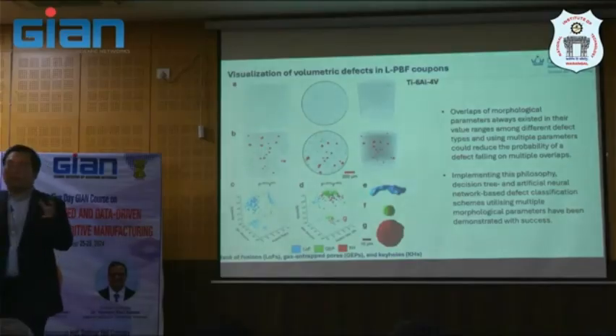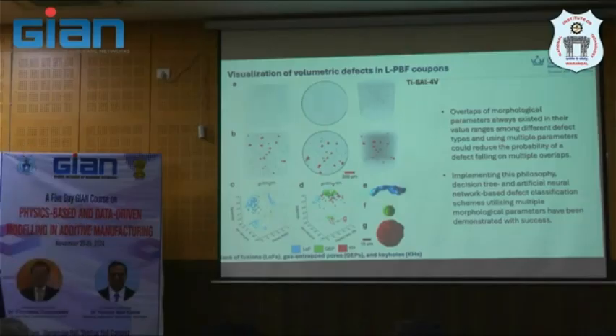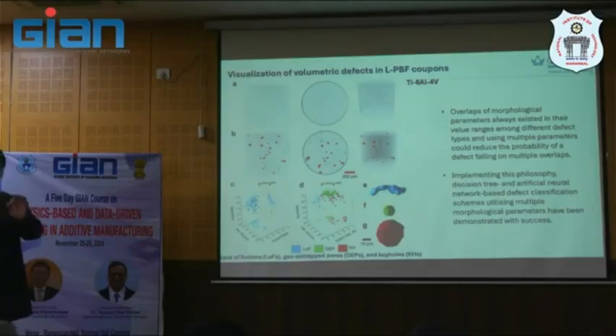So this is the statistics that you will get from these features. There are three important features to notice. The first one is lack of fusion. It will be elongated, and this is from XCT. Then there is gas entrapment porosity, which will be smaller pores. This may be from the atomization, small pores in the powder. And the next one is keyhole, or process-induced porosity, which is bigger in size. Again, we're talking about a size of 10 microns to about 20, 30 microns.